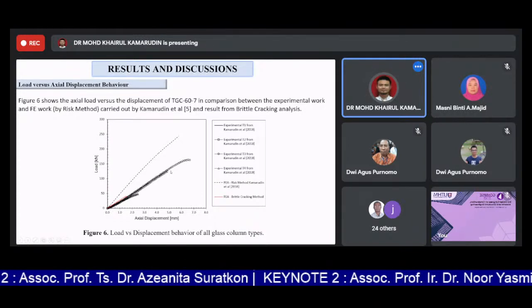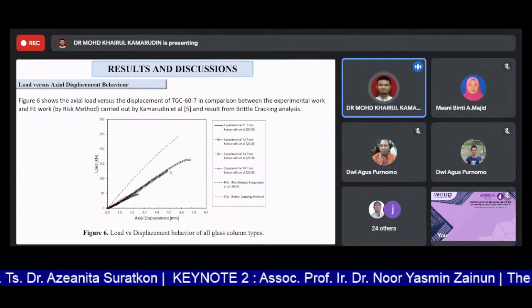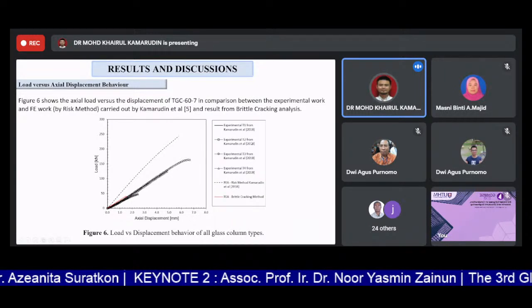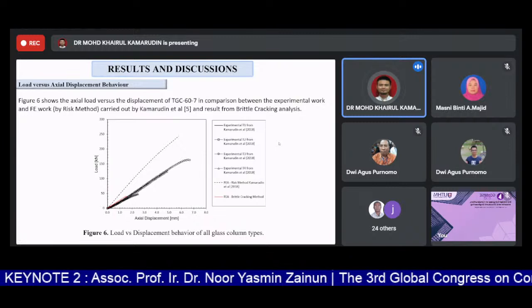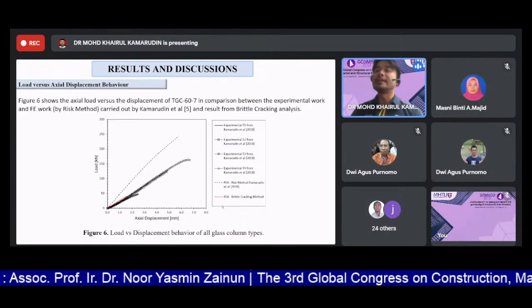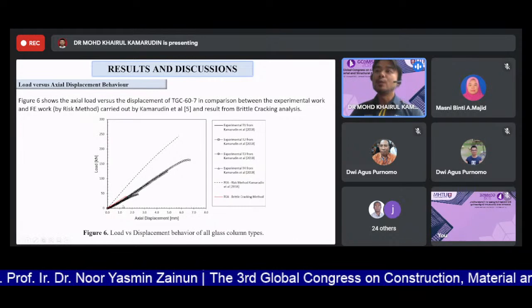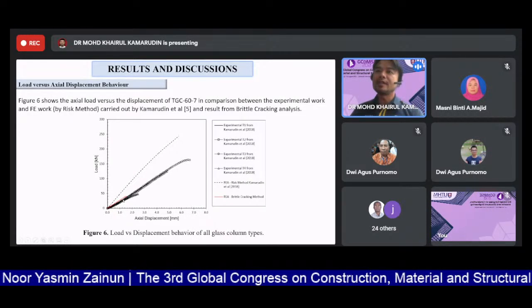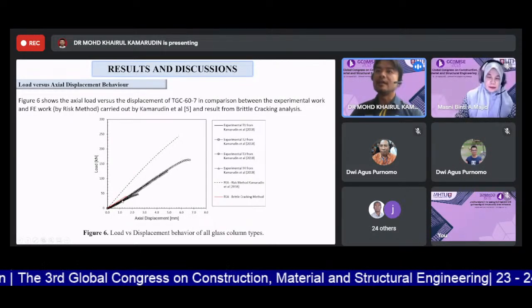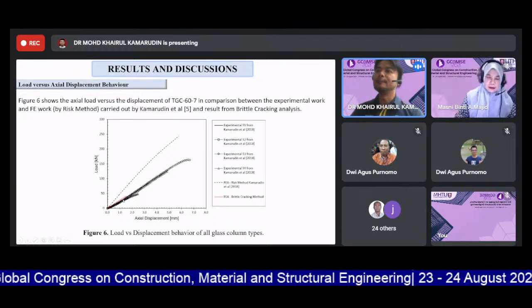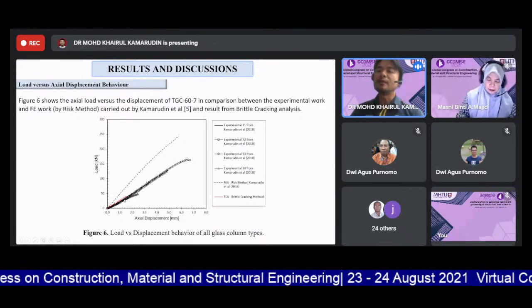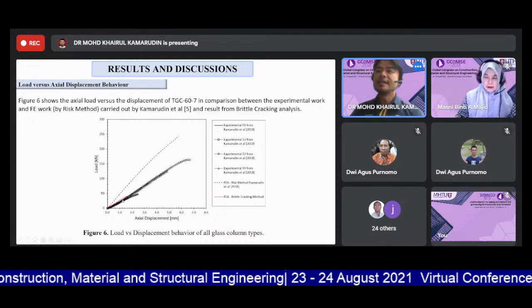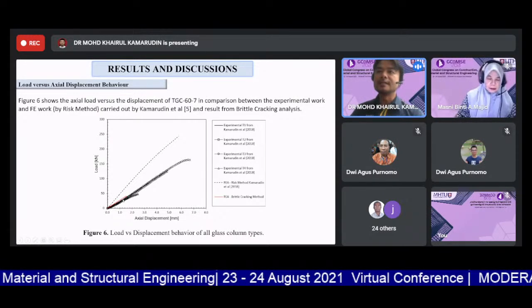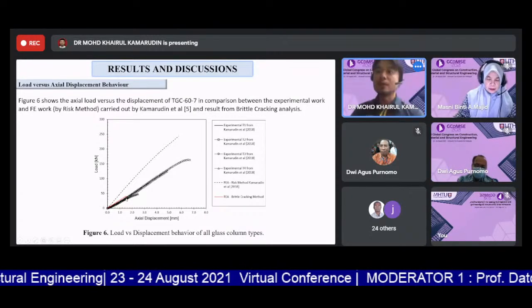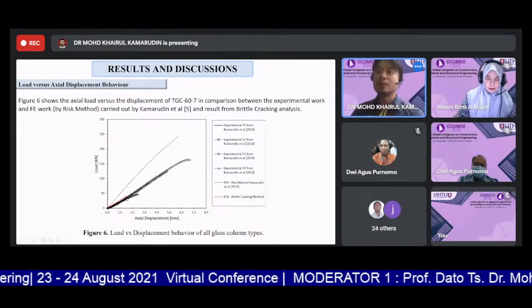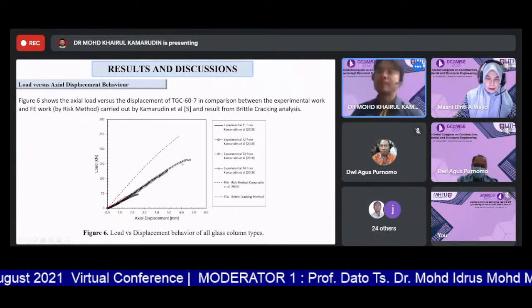So for this paper, we wanted to enhance the exploration in the FE by using this brittle cracking method, and we managed to capture quite a significant result with a quite apparent gradient of stiffness of the glass. It's just that the result we got is an estimate to compare to what we had from the experimental work.